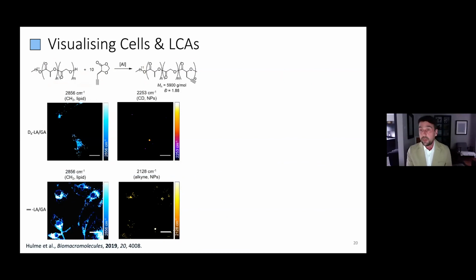We also do other applications in terms of our old biomedical collaborations. This one on the left is a collaboration with Alison Hulme, where we looked at appending alkynes using our LA/GA-based system into the framework. These alkynes are much stronger reporters for Raman spectroscopy, and because there's a cell-silent region to Raman spectroscopy, you can actually visualize inside cells. The top line here is the traditional deuterium-based system, whereas the bottom line shows how much stronger a signal we get from the alkyne-based systems that we've designed.